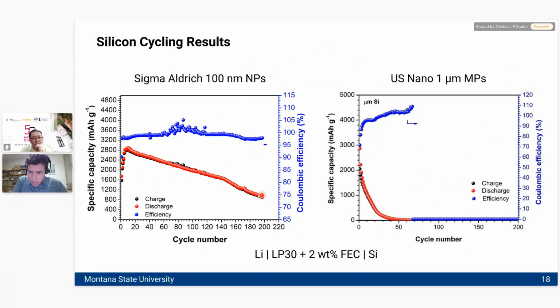But let's look at the discharge capacity. It's clear that you can get very, very high numbers of, say, 2,800 milliamp hours per gram. This is about 10 times the amount that you would get in a graphite cell on a per gram basis. But that number does not stay remotely stable. It falls relatively quickly with cycling. By the time you get down to 200 cycles, you're at less than half of what you started with. Now, the data I'm showing you on the left side are actually some of the best data we ever collected in our early studies of silicon. We scanned a lot of different potential precursor materials across different sizes of nanoparticles, different suppliers. These are some of the best data that we collected.